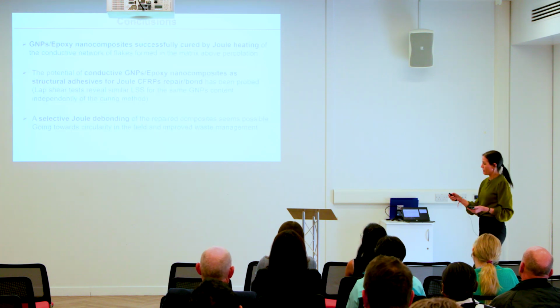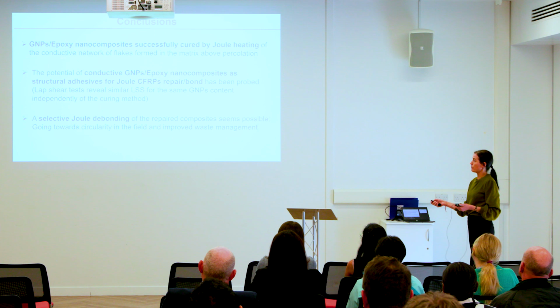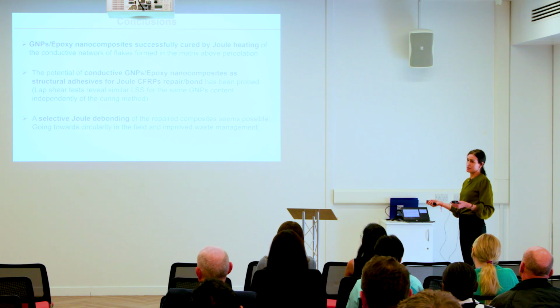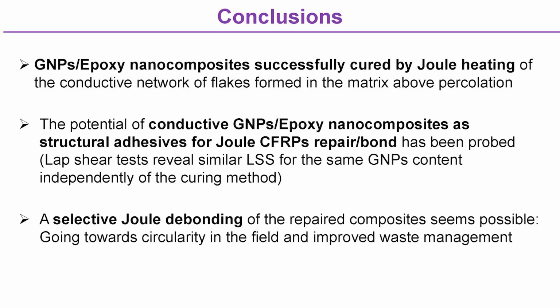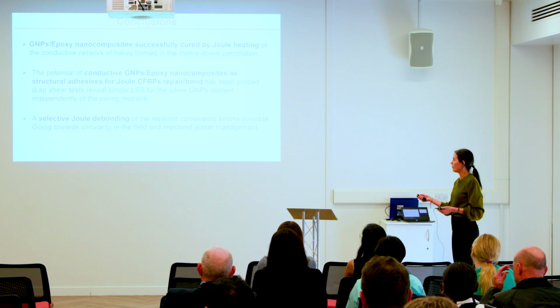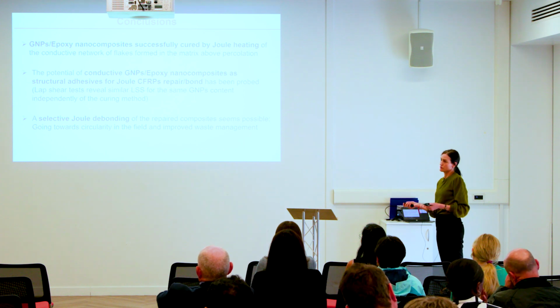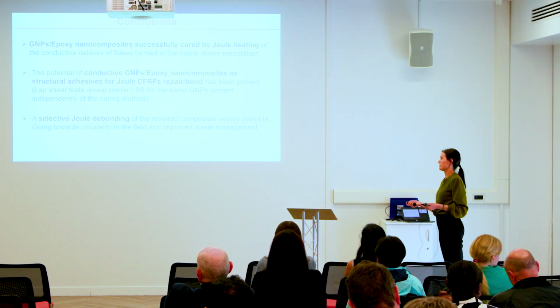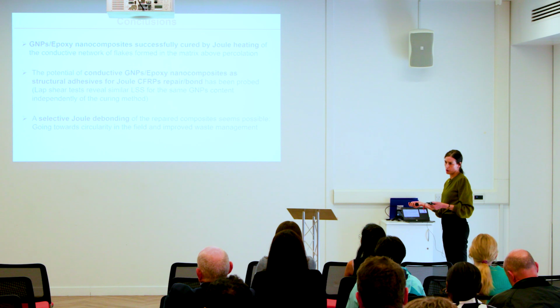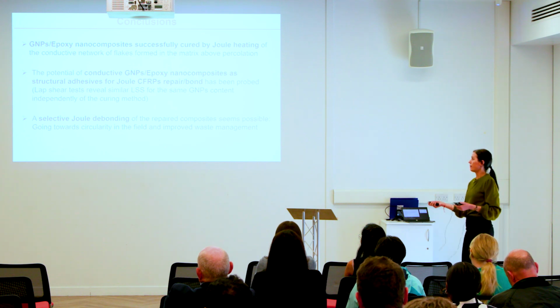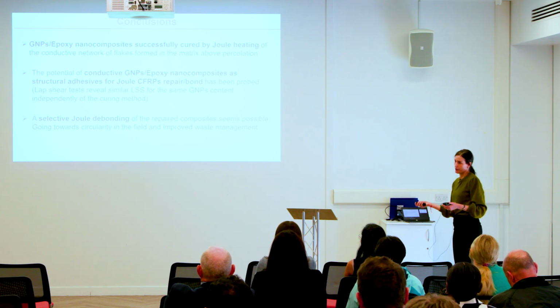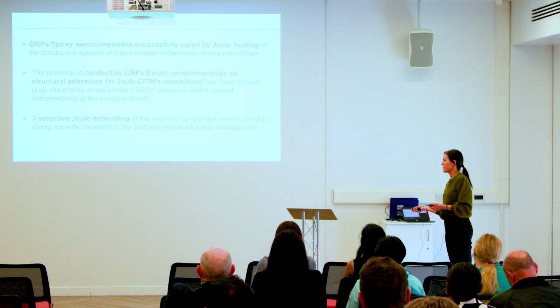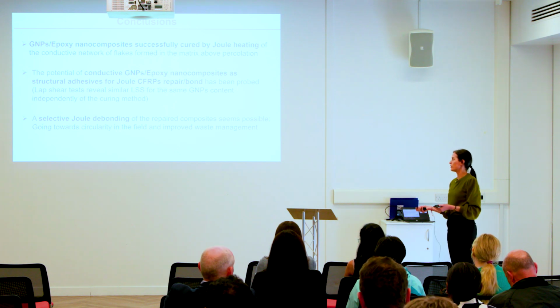So summarizing, we've seen that these graphene epoxy nanocomposites can be successfully cured by Joule heating of the conductive network of flakes formed in the matrix when we are above percolation. We've seen that these nanocomposites seem to have great potential as structural adhesives for Joule composites repair or bonds, and we've also seen that a selective Joule debonding is possible, going towards circularity in the field and improved waste management.